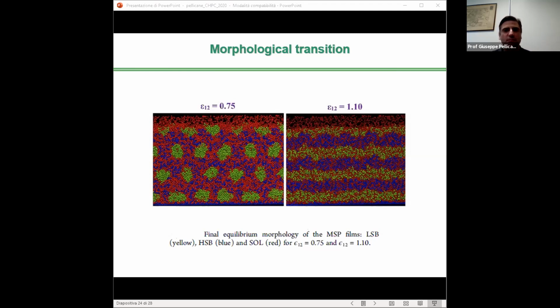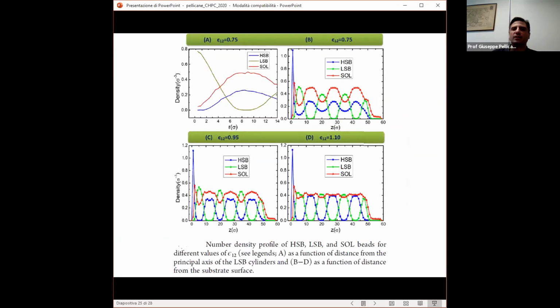Our conclusion is that for poor solvent conditions, the volume fraction of HSB is dominant over that of LSB, which leads to the cylindrical arrangement of LSB beads that we've shown before. Now, to get a better understanding of the distribution of solvent in the LSB and HSB domains, the number density profile of the three different types of beads, Sol, HSB, and LSB, is considered for different values of epsilon 1, 2, as you can see in this figure.